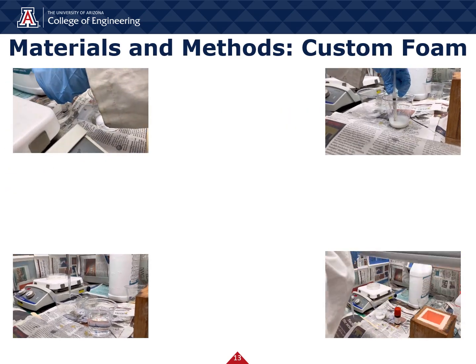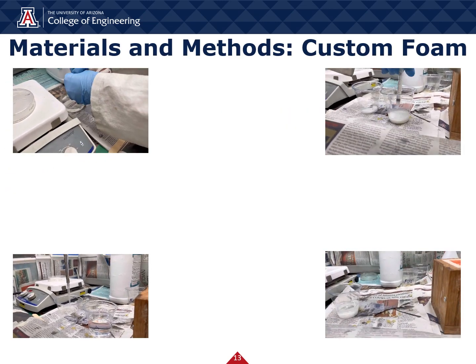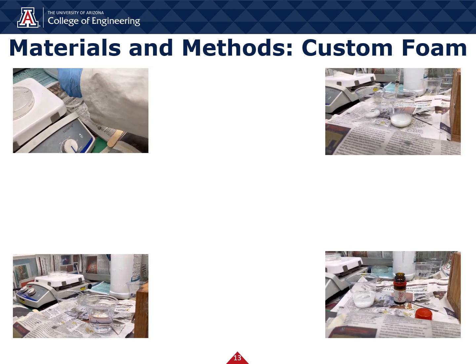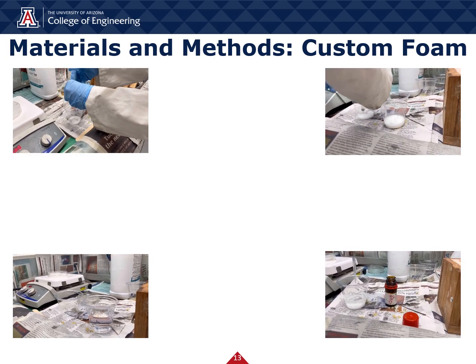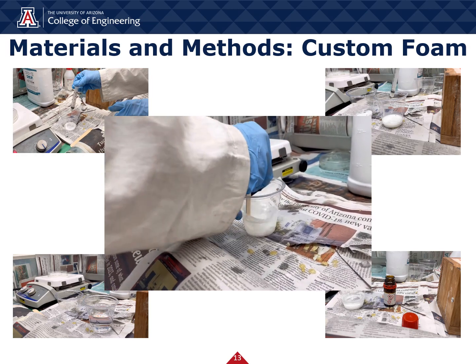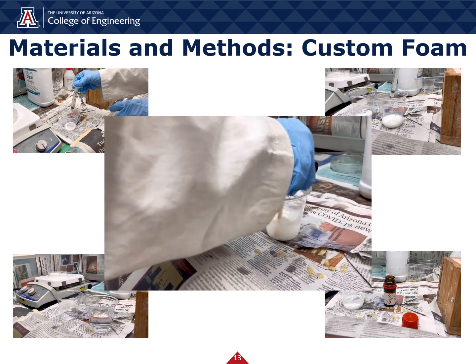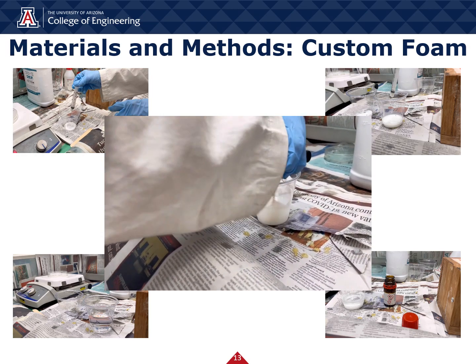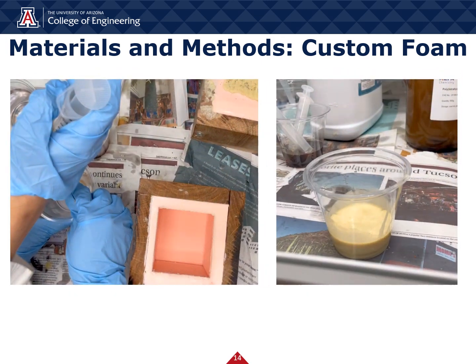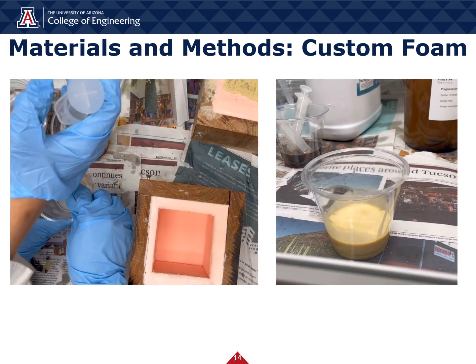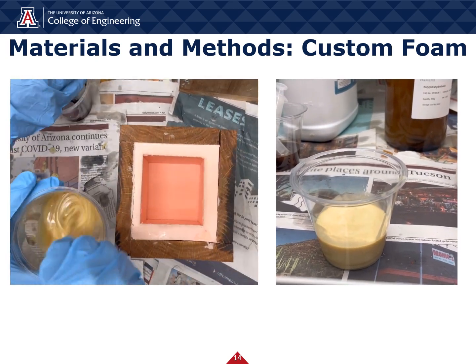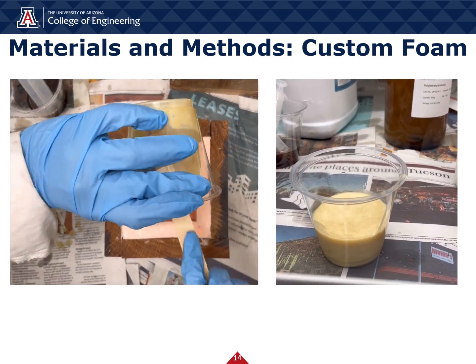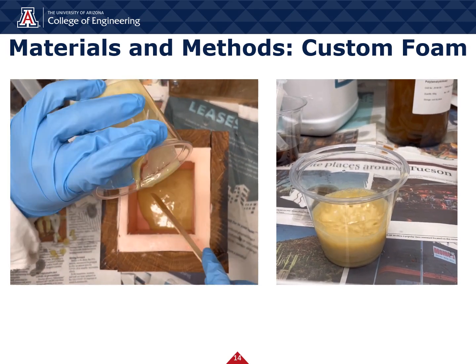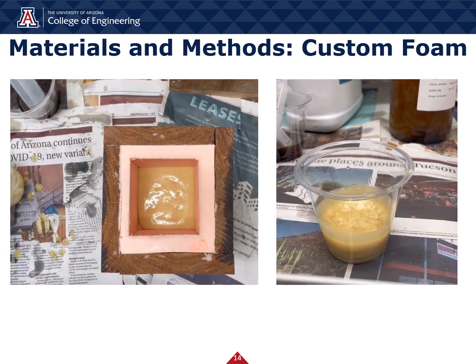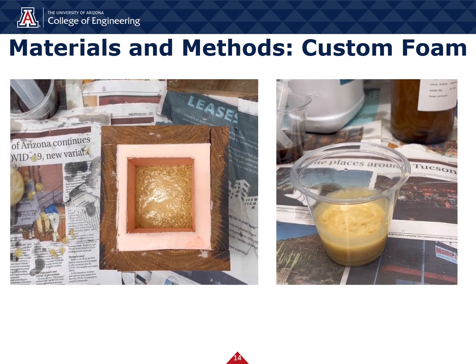The B side of the custom formulation was made by adding water, DMCHA, PTMEG, and surfactant to a clear cup. This mixture was then thoroughly stirred and left in the fume hood to off-gas for 2 minutes. Here the MDI solution is added, which reacts with the polyol exothermically. During the reaction, the mixture expands, releases energy, water vapor, and CO2, and then solidifies.